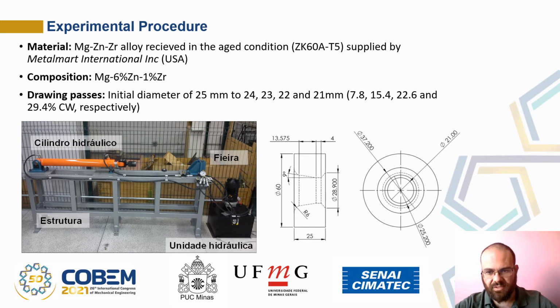The material which was used is a magnesium zinc zirconium alloy, which was received in the T5 condition, which is an aging heat treatment. The composition of this alloy is given in the slide: 6% zinc and 1% zirconium. Drawing passes were performed starting from an initial diameter of 25 millimeters and reducing to 24, 23, 22, 21, which corresponds to 7.8, 15.4, 22.6 and 29.4% cold work, respectively. All operations were performed at room temperature.